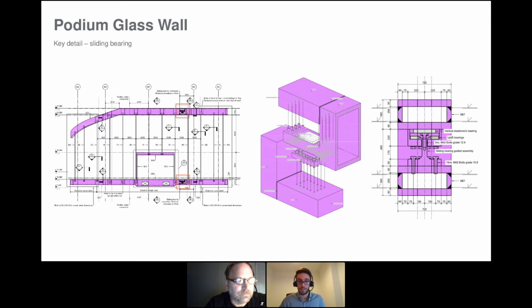Another quite important detail we developed was the sliding bearing to connect the top and bottom steel beam, especially in the east elevation where they are completely straight and flat. Clearly, we wanted to avoid too much load being transferred because of temperature variation, increase or decrease, especially because the axial load generated in the beam, because of the eccentricity of the beam to the connection of the concrete column, would have generated very, very high shear and therefore moment in the column. So what we had to do was cope with this displacement and try to absorb it with a sliding bearing detail. To minimize the friction and the residual axial force exchange, we developed this